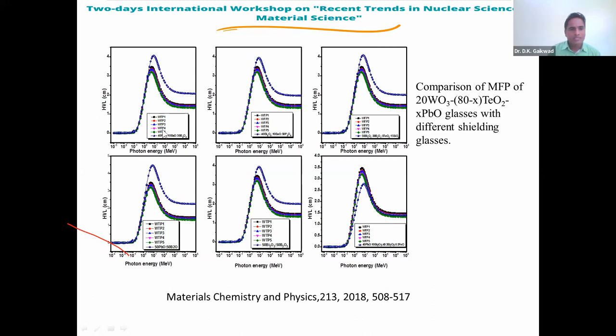Okay, so we compared our study with the lead glasses. You can observe in all the figures that the HVL of our sample in the low energy range is comparable with the other glasses, but at high energy it is very high, right? So we can say that the radiation shielding capability of our glasses is comparable, and we have found the radiation shielding capacity of a newly developed shielding glass.